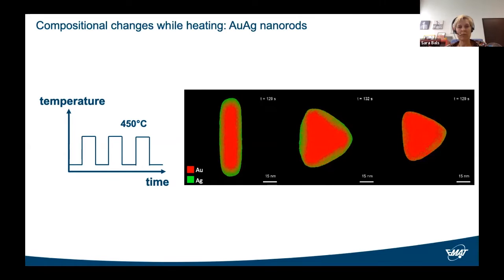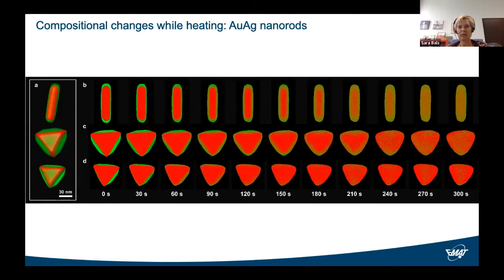And if we now want to compare between the different systems, this slide is probably easier, because what we will see is that the alloying is very much alike for the nanorod and the symmetric nanotriangle, which suggests that the shape is not so much important. But we see that the alloying for the asymmetric nanotriangle, which also has slightly different composition, starts much faster. And so that is a motivation to perform these measurements really at such a local scale for different nanoparticles.